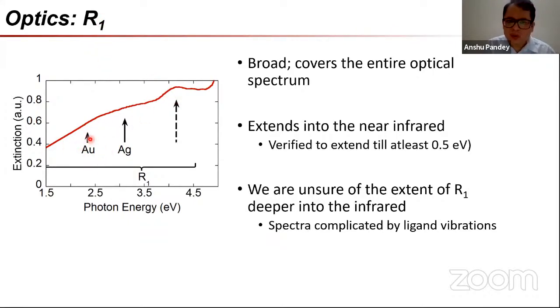What has happened is that the normal Mie-like resonances of gold and silver disappear. And instead of that, we have this very broad background, which seems to cover the entire optical spectrum. In cases, this can be very narrow, located just around 4 eV or so. In other cases, which are the more interesting samples, which we studied in more detail, this seems to span quite a bit of spectral width. We verified it till at least half an electron volt, and we are unsure whether it extends still deeper, as our spectra at that point get fairly complicated by ligand vibrations. Frankly, we don't know if it goes any deeper.